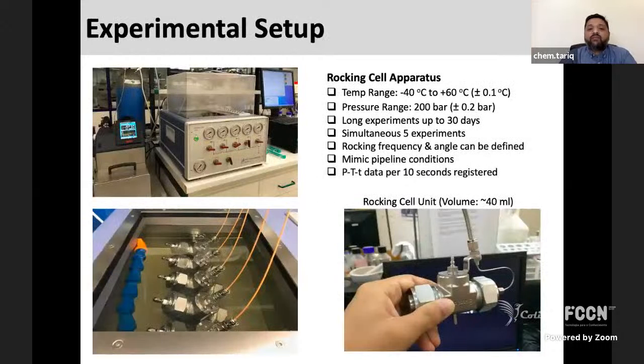We have used this experimental setup, called the rocking cell apparatus, which is a very specialized instrument to test the formation of hydrate. It can work with a standard pressure of 200 bar, and it can work in a large range of temperatures. We can perform five experiments simultaneously with a very low quantity of sample.